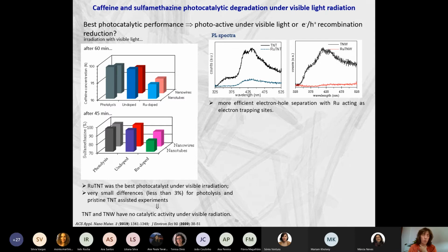When we look at the photoluminescence spectra of these powders, and these are emission spectra, we can see that, in fact, when we have the ruthenium in the structure, we have a very low emission spectra. And this is because we have a more efficient separation of the electron hole in the system. Why? Because we have ruthenium there that acts like electron trapping sites. And only after all these studies, we are able to propose a mechanism for the activation of these materials. In this case, we have the role of ruthenium species that are here in this forbidden zone, and then help us to have a better photocatalyst system.